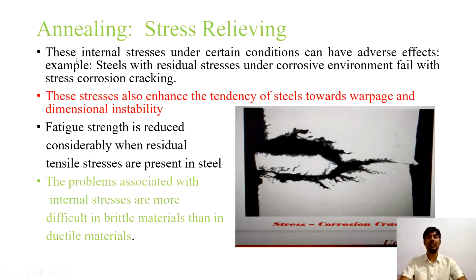Again, these internal stresses under certain conditions can have adverse effects. As we know, whenever stress is maintained or is present in any part of a component, it may cause a very bad effect on the material structure. Material may crack or corrode, or some other defect may also occur if we do not remove these stresses. Steel with residual stresses under a corrosive environment fails with stress corrosion cracking, as we have discussed earlier. These stresses also enhance the tendency of steel towards warpage and dimensional instability.